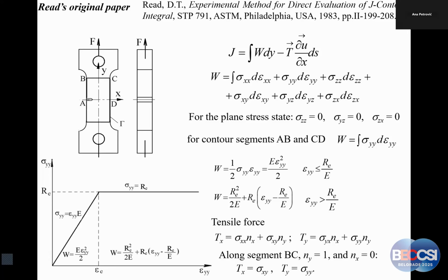You can see this figure here. This is a simple tension of a panel specimen, let's call it. It's not exactly a specimen, but sorry, it's a plate or panel. We use different terms. In tension, and there is a crack here, and there is a path all over this crack, the so-called outer path. Outer because you can see it goes from A on the outer surface, then it crosses the panel all the way back through the outer surface, once again crossing the panel and going back here as the outer contour. One of the assumptions in this story is that behavior of material is elastic, ideally plastic, although corrections are possible if there is some kind of strengthening.